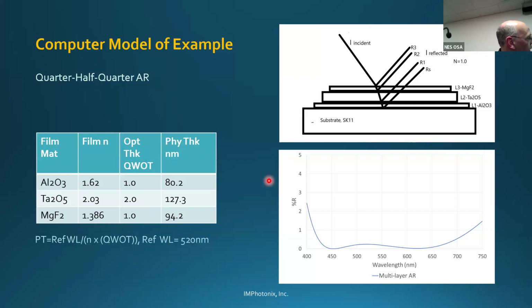These are the visible materials. As the incident light reflects off each surface, the top layer, the first layer, is aluminum oxide, layer 1. The second one is tantalum. Third is mag fluoride. The reflection off each of these layers produces a wave front that either interferes constructively or destructively. For an AR coating, we design for destructive interference; for a high reflector, we want constructive interference. But here we want to reduce reflection, so we're designing with destructive interference. That design gives us a model that looks like this curve, where we're getting less than 0.5% average from 450 to 650. The spec on the print was 1%, so we're well below that.